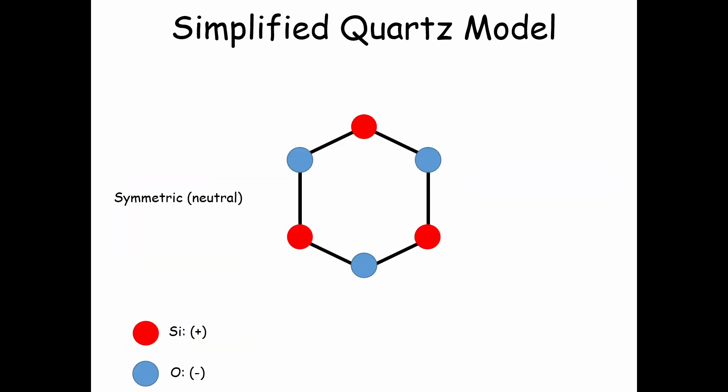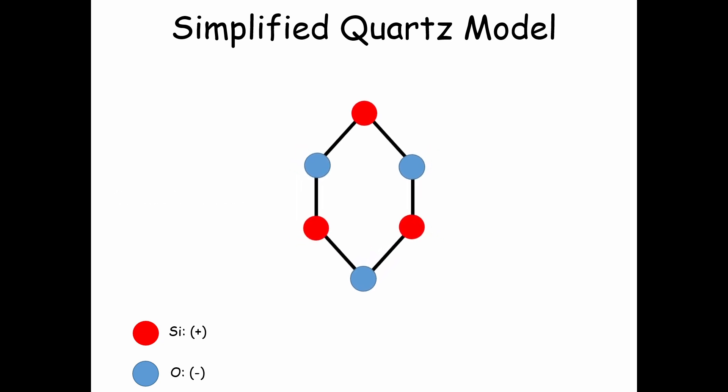Let us now look at an intuitive picture of piezoelectric effect. This is a simplified model of quartz, in which charge distribution is neutral. We can see that there is inversion symmetry here. The red dot represents silicon or positive charge, and blue represents oxygen or negative charge. On application of stress, the crystal is deformed, breaking the symmetry.